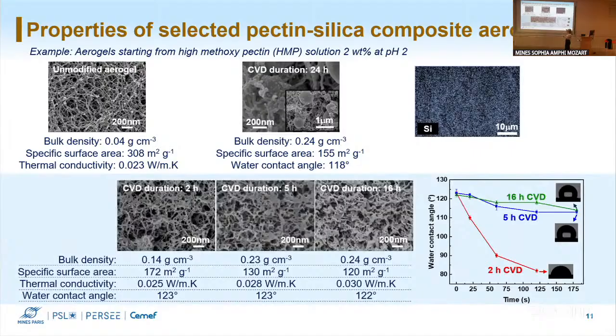So moving inside the material, I suppose that it's not that we get more hydrophobicity, like more deposition of silica or something, but this big difference in contact angle we mainly attribute to the polishing, so the roughness of the surface after polishing. Yeah, between neat aerogels and the other one, but are you sure that only the polishing, and there is not another thing which can explain the increasing of angle? It could be the roughness of the surface itself on the surface of the aerogel and the interior of the aerogel, that we know that the roughness is more inside, but we cannot distinguish what it could be. And we tried to cut better, but we did not. It's very difficult. Okay.